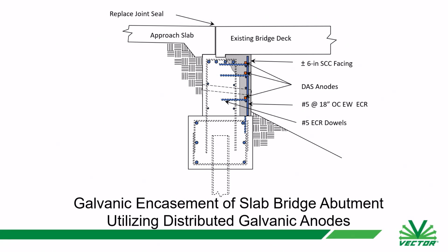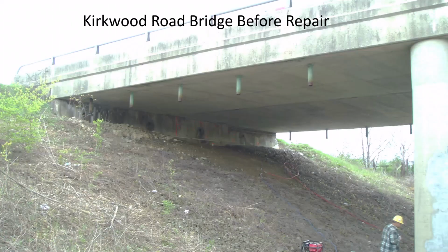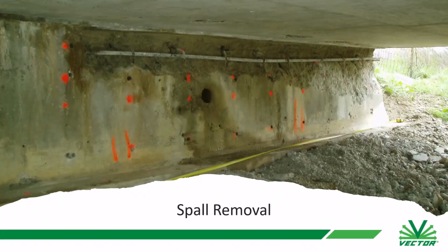And so the idea was, what can they do to affect the abutment from a structural and a corrosion protection standpoint in a very positive manner. And so the idea here is that they would basically put a 6-inch face on the abutment with new reinforcing steel and what they called distributed anodes, or these long anodes. So this is one of the projects that goes back to 2005. Same kind of situation as the other pictures that you saw.